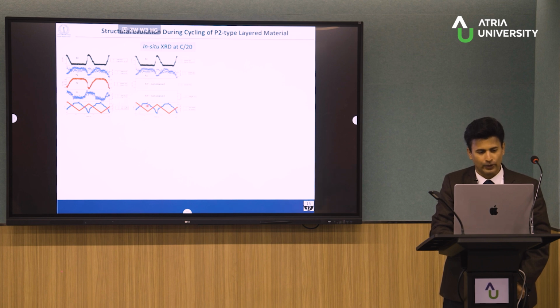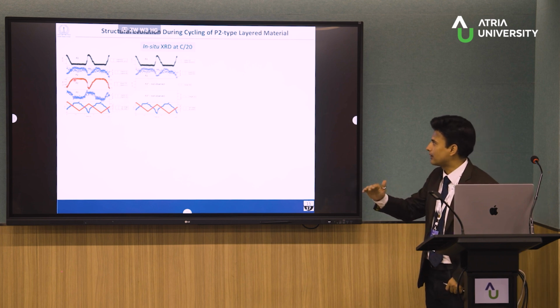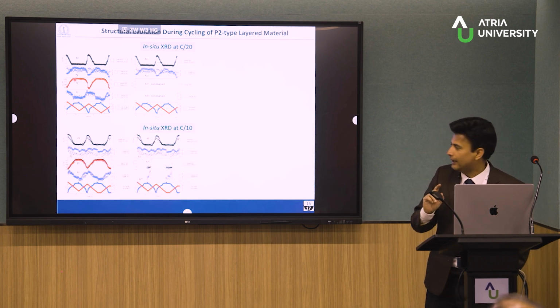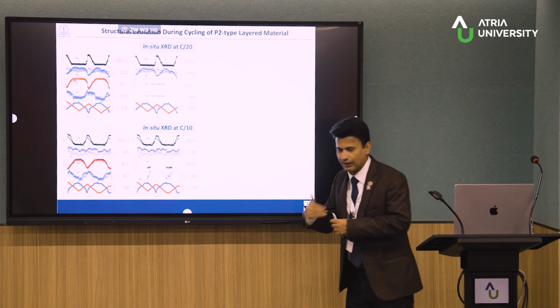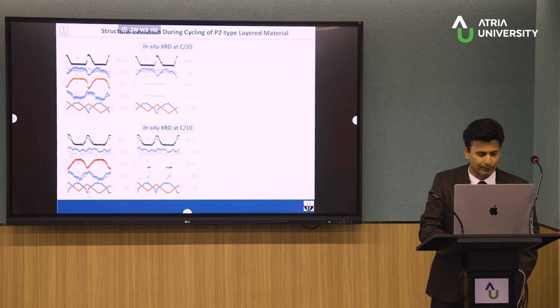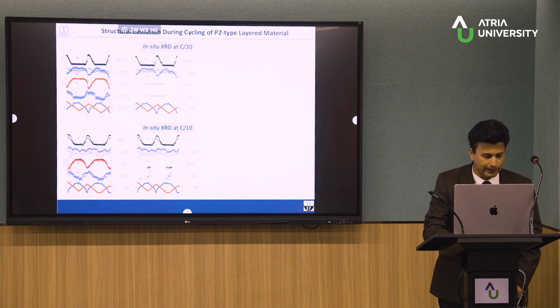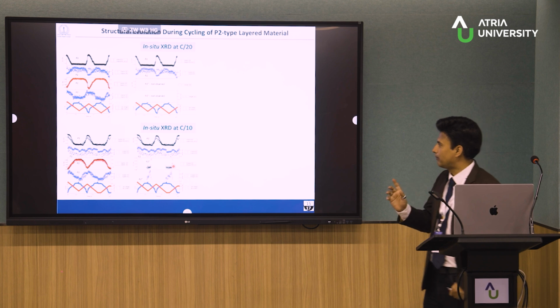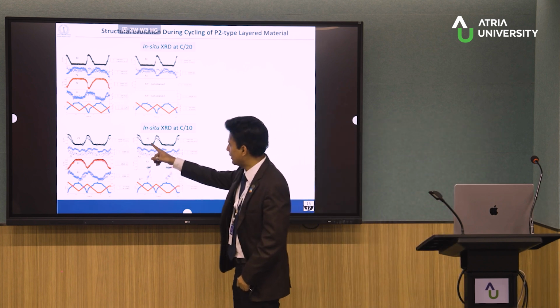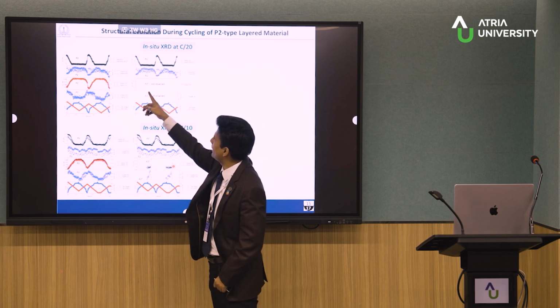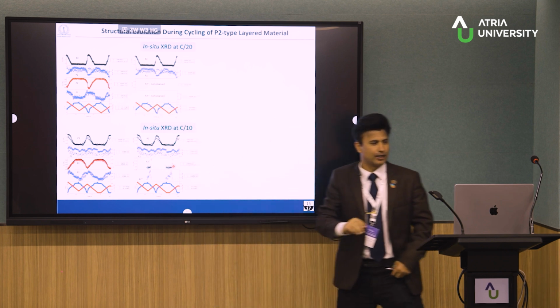Now, in this case, you can see that in some cases the P double prime 2 is not forming at all. So in the case of C/20, it is only the P2 kind of phase and the a, b, c parameters change continuously. But in the case of C/10, when we do the charge and discharge a little more rapidly, what happens? This is the voltage profile, the blue one. This is desodiation, sodiation and so on. You can see the P2 phase amount increasing and decreasing, but around this composition you can see a sudden appearance of P double prime 2. So at high rate we can see both P2 as well as P double prime 2. At the low rate we don't have any P double prime 2. Single phase, double phase. So there are two kinds of reaction.